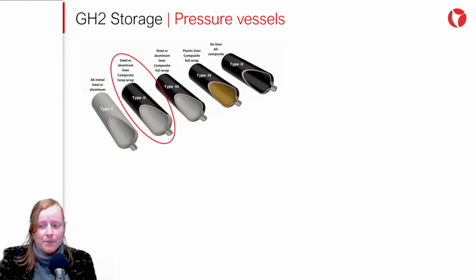Next is Type 2. These cylinders are metallic, wrapped in composite material rings. Like Type 1, the ratio of hydrogen to cylinder mass is low. These containers are also heavy and thick-walled. Standard tanks generally have a maximum pressure of 300 bar.